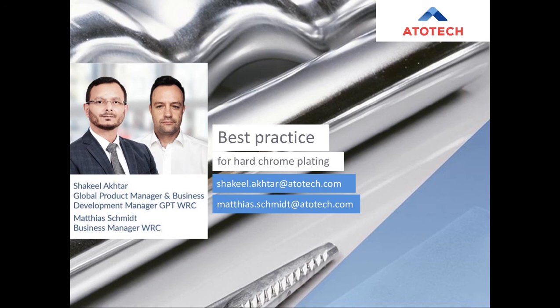Can your Dynachrome ion exchange system be used on conventional processes? Yeah, also a very good question. Usually, from the technology point of view, it can also be transferred to conventional plating systems. The catch is, in order to run ion exchange, the solution has to be diluted in order to not destroy the resins with the very highly oxidizing chromic acid. So it has to be diluted 3 times with water.